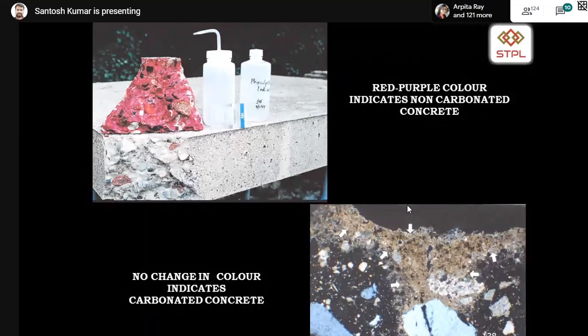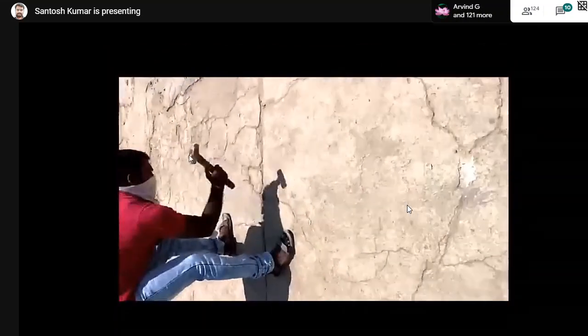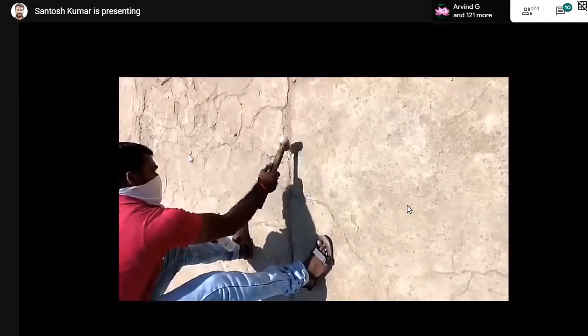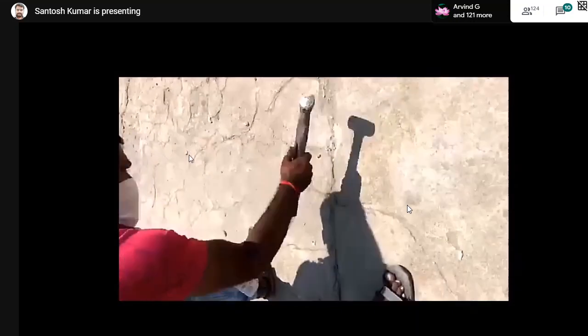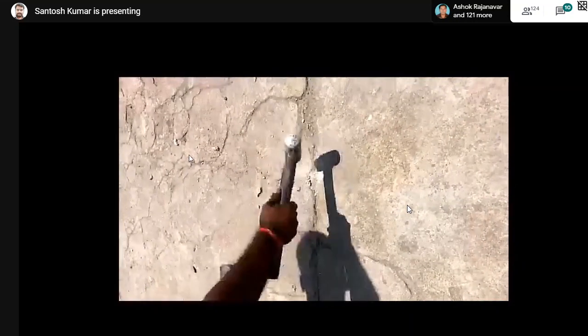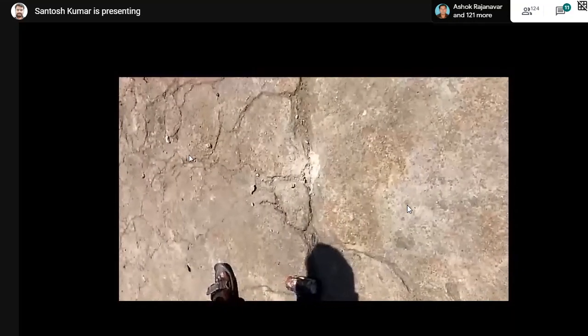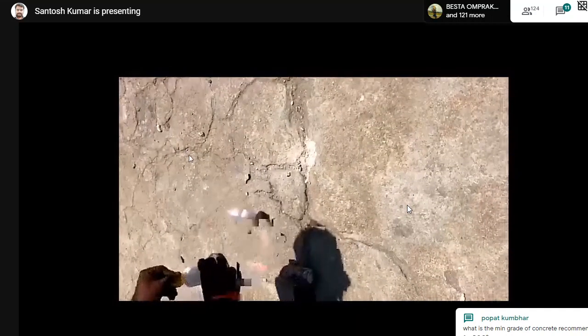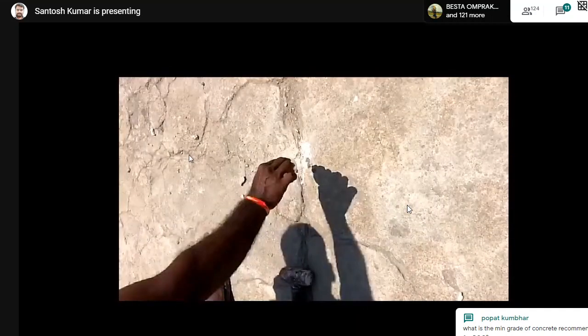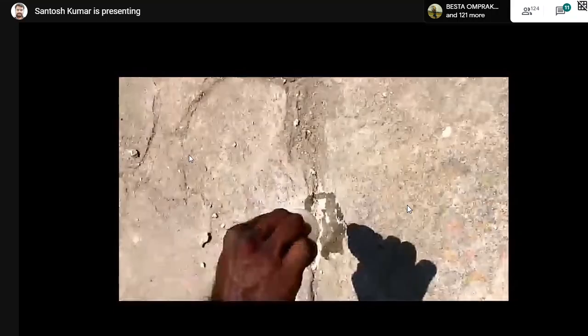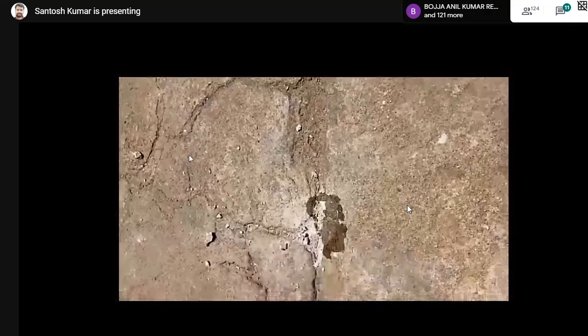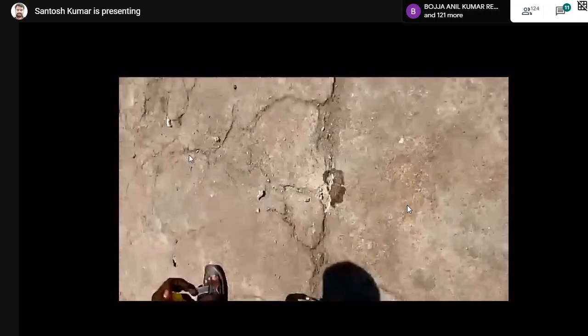I just want to show you a video which we have done on the pavement. You can see here in front of our laboratory, we have chipped the concrete on the surface of the pavement and we have sprayed this phenolphthalein solution mixed with ethyl alcohol and distilled water. And you can see there is no change in the color. So that means your concrete is carbonated.